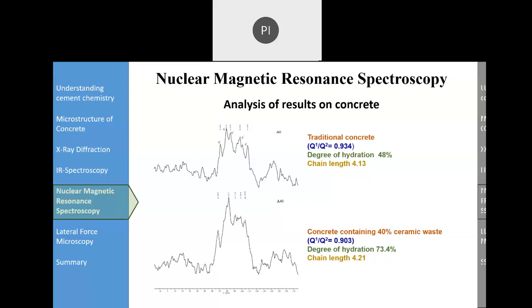In the first type of concrete, the degree of hydration is 48%. In the second type of concrete, we got the degree of hydration 73.4%. Now this we cannot get directly from these mechanical properties and durability properties. Now, if we know that in one concrete the hydration is only 48%, in another concrete hydration is 73.4%, then it is quite obvious that the concrete in which the hydration is more, that will give us more strength, that's better concrete.